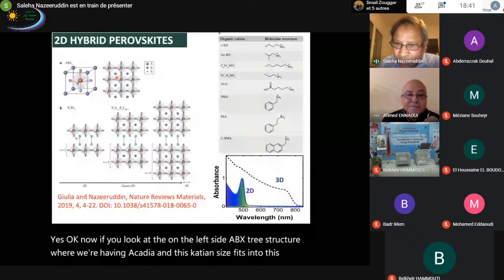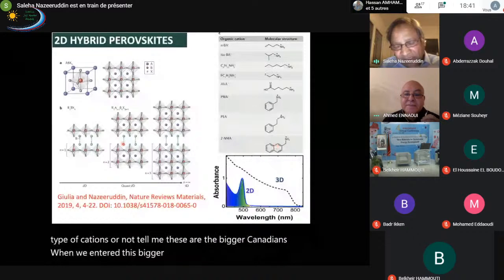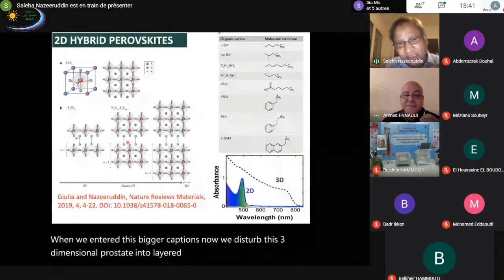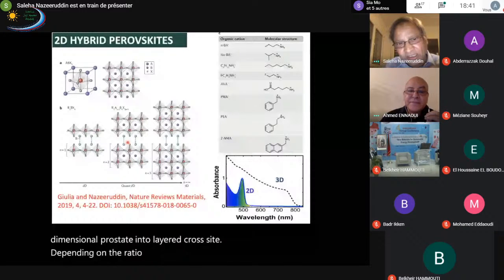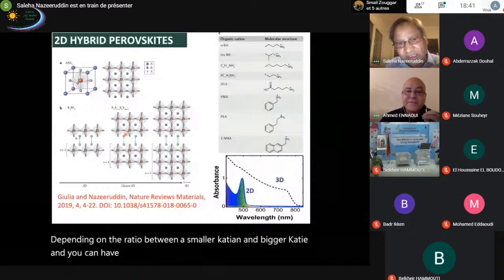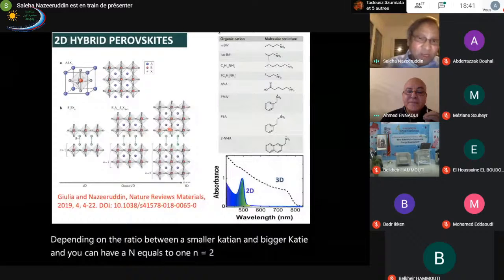However, if we change this cation to a bigger cation shown on this table, NBA, that's butyl ammonium, isobutyl ammonium, phenylethyl ammonium, or naphthalamine, these are the bigger cations. When we insert these bigger cations, we disturb this three-dimensional perovskite into a layered perovskite. Depending on the ratio between the smaller cation and bigger cation, you can have N equals 1, N equals 2 layers, N equals 3 layers. The maximum we synthesized was N equals 6. So now you have a beautiful opportunity to control the perovskite material itself with the number of layers.